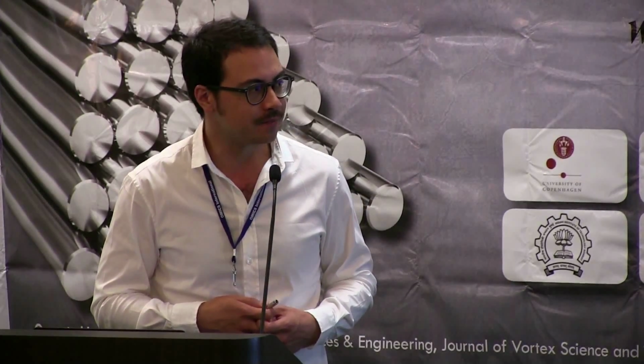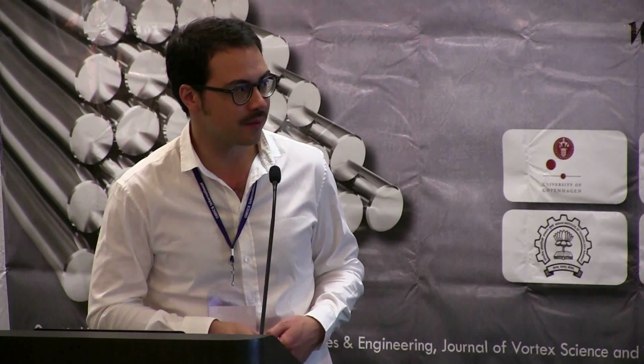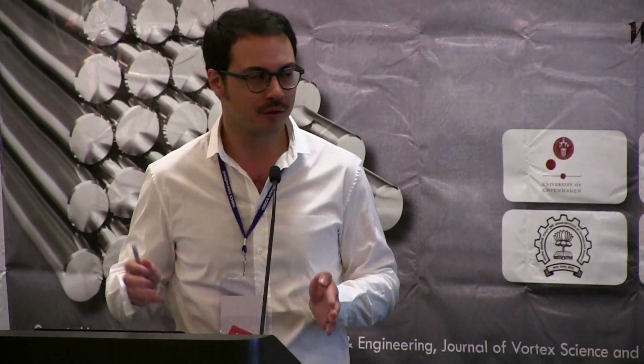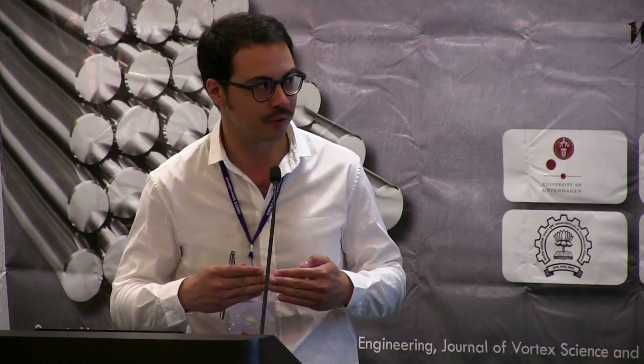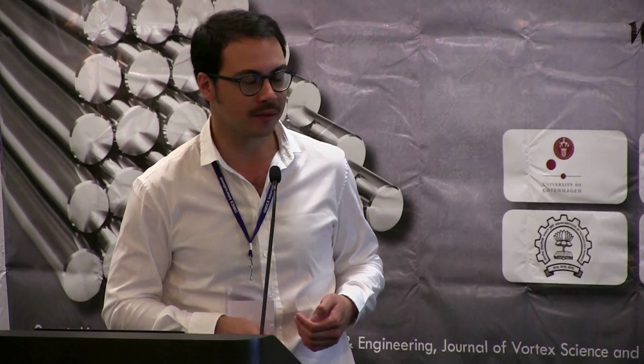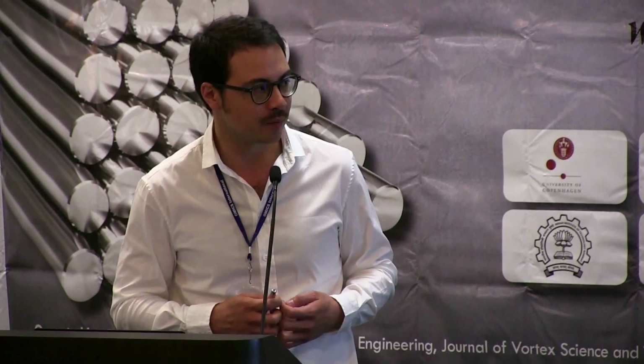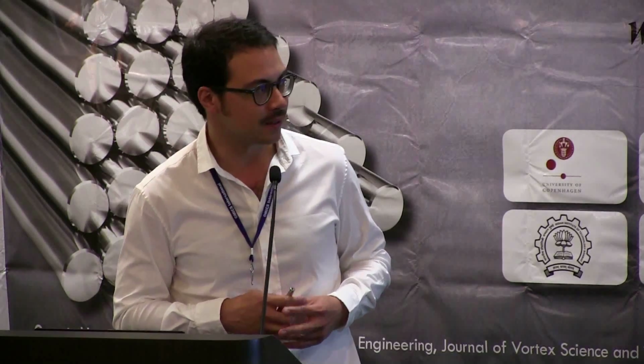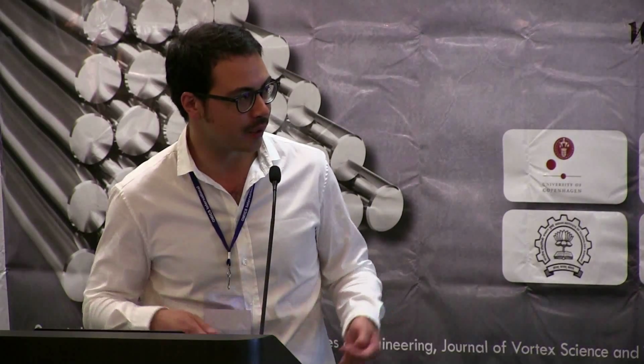You have this after the final heat treatment, but the problem is that when you have more activation cycles, the wire might get longer. So if you start with a wire of 100 millimeter length, after 100 activation cycles it might be about 104 or 105 millimeters long. So that's why the SMA training is made, so that you make a lot of activation cycles, so that you don't have this kind of drift, and afterwards you can apply it in technical or mechanical things with a high reproducibility. And yeah, this is the point we have investigated now.